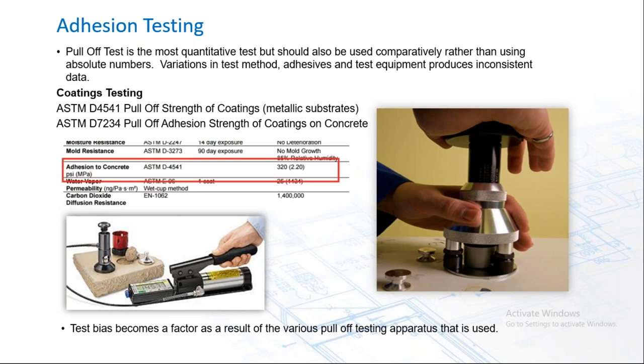Unfortunately, there are five different test apparatus, and a testing bias now becomes a factor as a result of the various apparatus that are used. But great, again, for a comparative test, where you have competing manufacturers on the wall, or you want to test the adhesion of the existing coating versus the effects of applying the new coating. But as an absolute number, there's not a lot of frame of reference there.